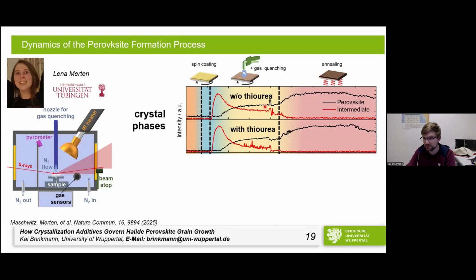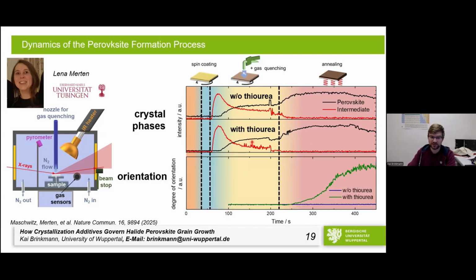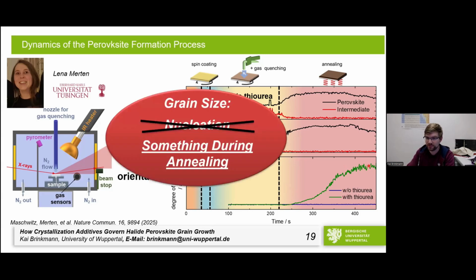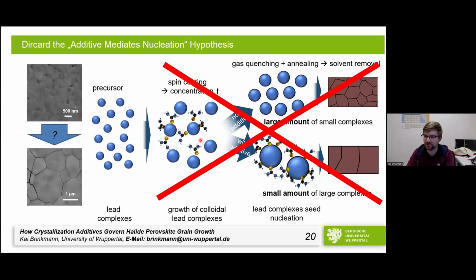This is different for DMSO. So this is something that we see in DMF and NMP. But what is most surprising is that this perovskite that occurs until the annealing starts looks exactly the same in terms of orientation and in terms of basically every parameter. And then we put it on a hot plate and suddenly things start changing like crazy. Which basically led us to the point that focusing on nucleation was maybe a very bad idea. So basically our original hypothesis went into the rubbish dump. And we started looking for what the heck is happening there on an already formed perovskite when you put it on a hot plate with an additive inside.